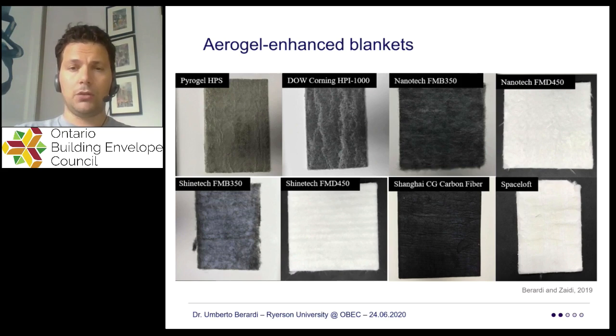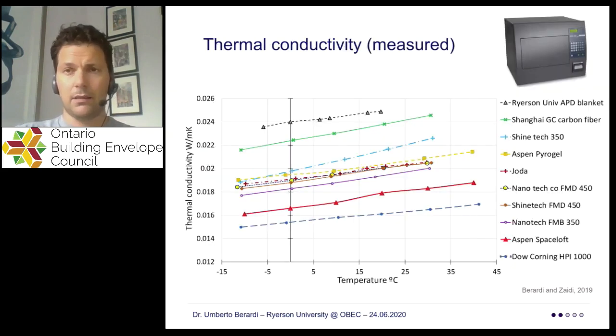So they have very good thermal behavior, and we've been testing these kinds of material properties in our lab. I need to confess that for some of these products, we found results that were higher than what those companies were declaring in the technical sheet. But without questioning, these products have a very low thermal conductivity compared to a lot of other products. And they are produced and sold these days as tiny layers of 1 centimeter, 50 millimeters or 20 millimeters that you can use, for example, for protecting thermal bridges.